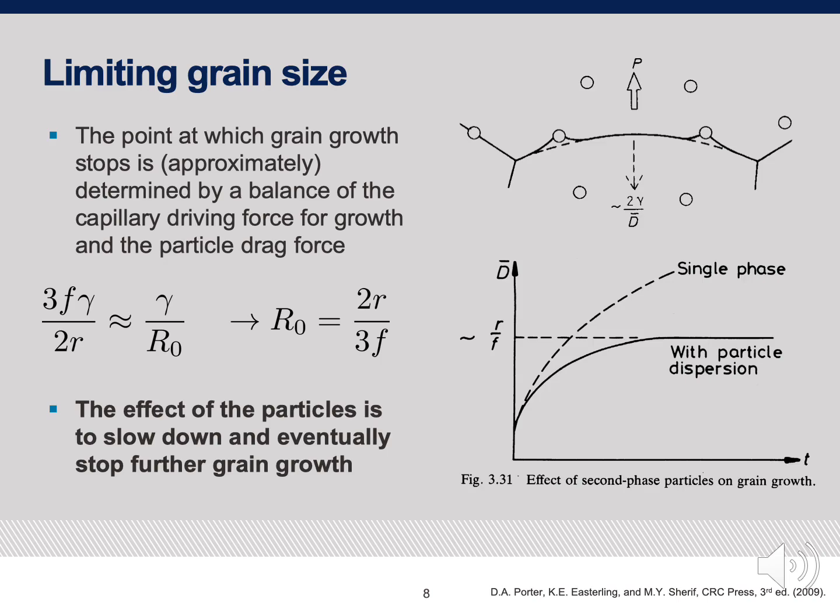So as time progresses, eventually the grain network will asymptotically reach this limiting size, which is proportional to the particle size, which is lowercase r. I suppose I forgot to mention this. The grain size is uppercase R, the particle size is lowercase r, the particle volume fraction is f, and so it's proportional to r over f. At long times, eventually, the system will strike this equilibrium, where the pinning force is balanced by the capillary force, and you achieve this limiting grain size.